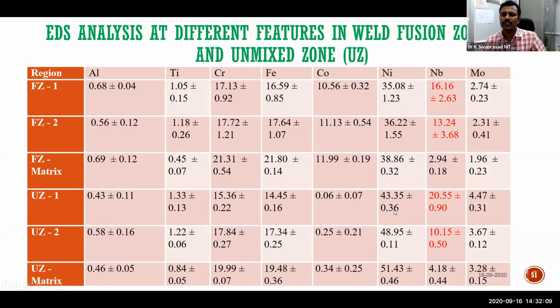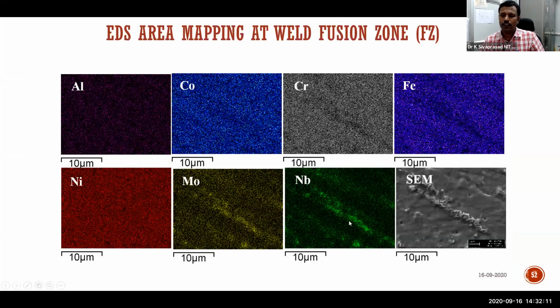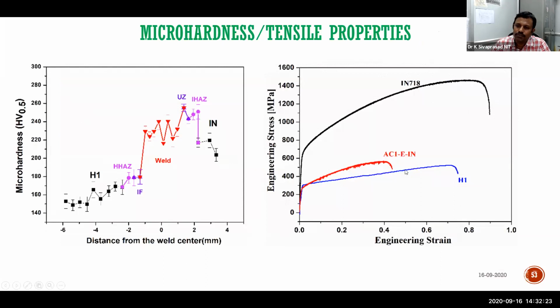So we have seen that niobium is distributed like in a line, but it is discrete. You can see patches through this SEM image. So that is the reason the property we got is higher strength. But as I said already, with niobium carbide and Laves phase formation in a network, ductility has come down in the fusion zone. Strength is relatively high because of hard phase formation, but ductility is reduced because of that.